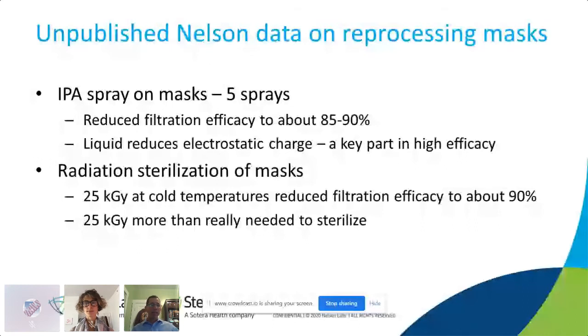The issue, and this is something I did not know because masks have not been my specialty in the past, is that the N95 rating, that extra bump up to N95, is usually based on an electrostatic charge that the mask material has. And as you reprocess those, mainly when it hits liquids, that will reduce or eliminate that electrostatic charge. And then you only have the material itself that is causing the filtration efficacy. So that does eliminate quite a few sterilization methods that use very high humidity or actual moisture, because it makes it harder to still obtain good data on the masks afterwards.